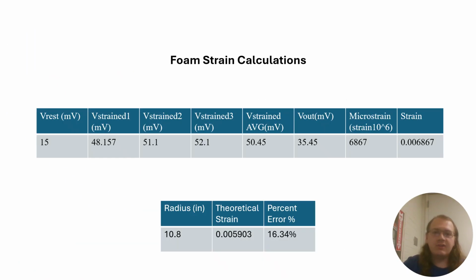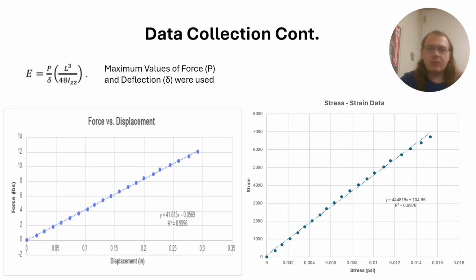After measuring the V strained 3 times, the average was calculated and turned into V out by subtracting the V rest. The V out, V in, and gauge factor could then be used to find the microstrain. The microstrain is 10 to the power of 6 times larger than the strain and was promptly turned into strain. Compared to the theoretical strain, the calculated strain only has a percent error of 16.34%, which is well within the expected range. Now for the 3-point bend test data.